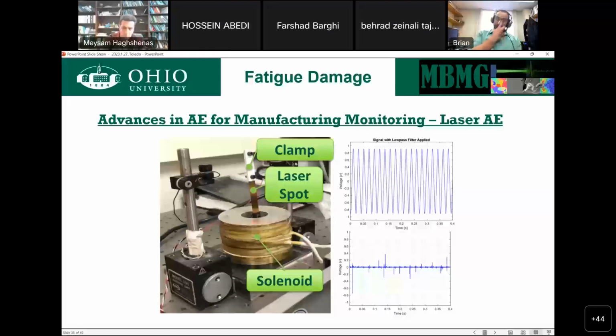What's nice about this kind of methodology is that the laser, depending on which one you acquire, will capture a larger range of frequencies than any traditional sensor can. With a traditional sensor, you can get some that are considered wideband that can get maybe 100 kilohertz to 2 megahertz. There are some that can go a little more than that. But the laser, the one that I'm using, can go from almost 0 hertz up to 24 megahertz.